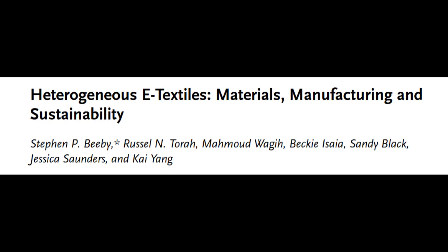What kind of inks or pastes are we talking about here? What's in them? Well, they contain the specific functional materials needed for whatever electronic device you're trying to make. So conductive materials are common, inks containing silver nanoparticles or carbon materials like graphene or carbon black or conductive polymers. There's the wires and electrodes. Exactly. Then you have dielectric materials, which are insulators used for capacitors or just isolating layers. And you can have piezoelectric or piezoresistive materials formulated into inks for making printed sensors. And I guess you need other stuff in the ink, too. Oh, yeah. Crucially, these formulations also contain additives, binders, solvents, viscosity modifiers that control the ink's properties. They make sure it flows correctly for the chosen printing method, adheres well to the fabric fibers, and cures properly.